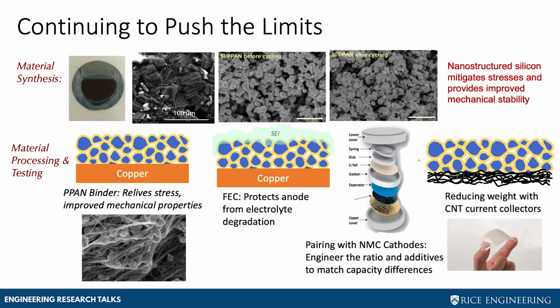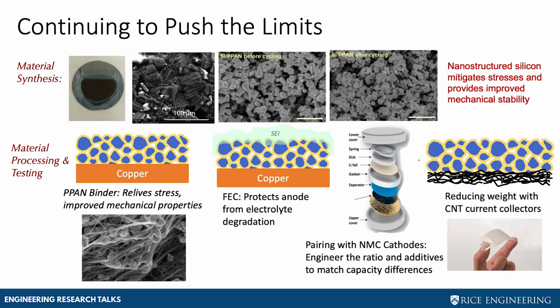So hopefully I've shown you that we're really pushing this limit. This idea of nanostructuring silicon is able to mitigate some of those structural stresses and provide some of the mechanical stability. I've shown you that by introducing that polymer binder, we're able to improve the mechanical properties. Using additives and coatings, we're able to protect the electrode from parasitic reactions. We can also pair this with high-performance cathodes and reduce the weight. So ultimately, we're looking at being able to create flexible, lightweight batteries.